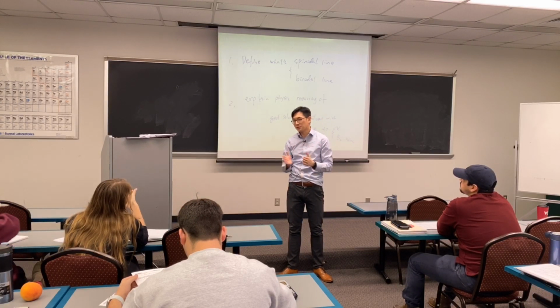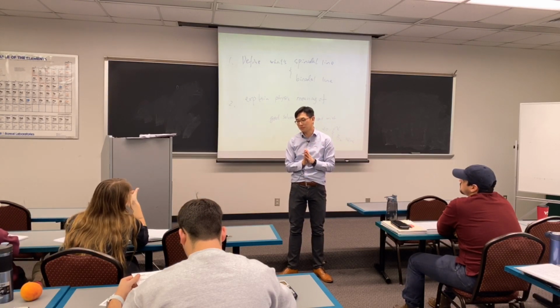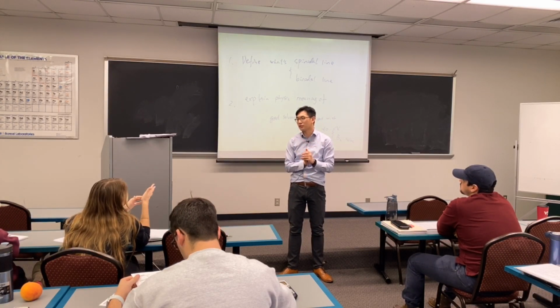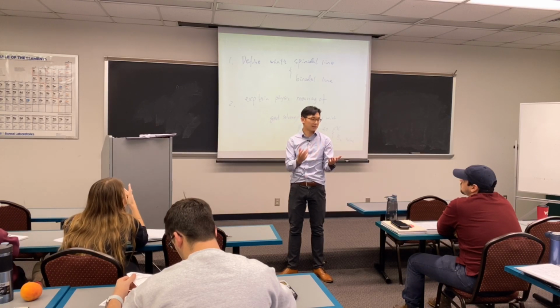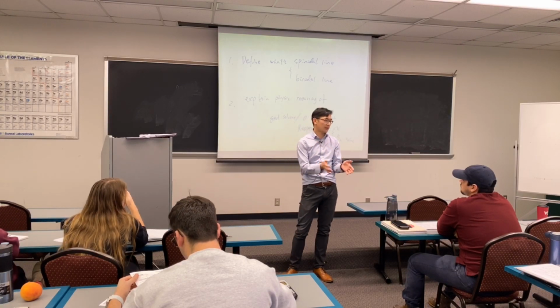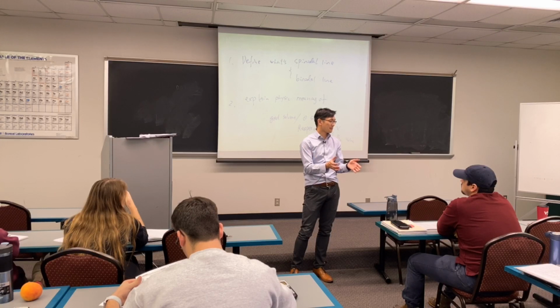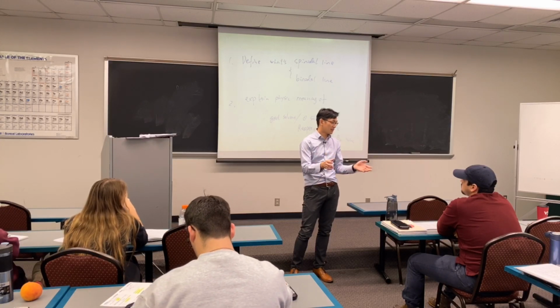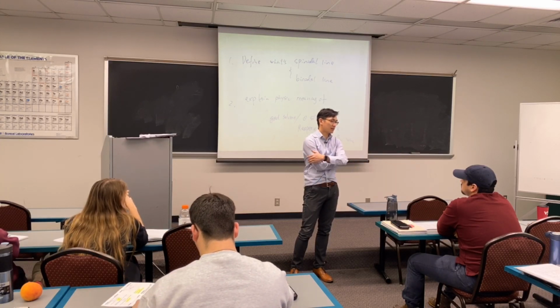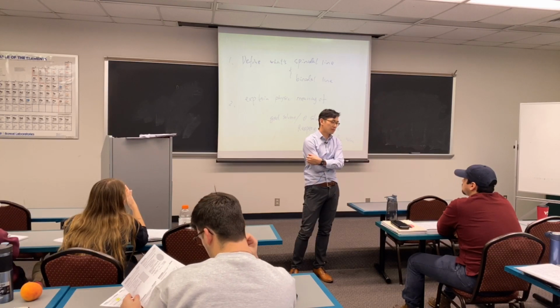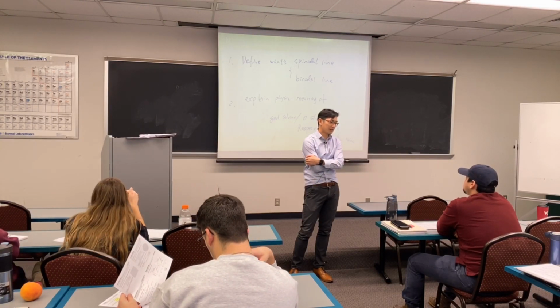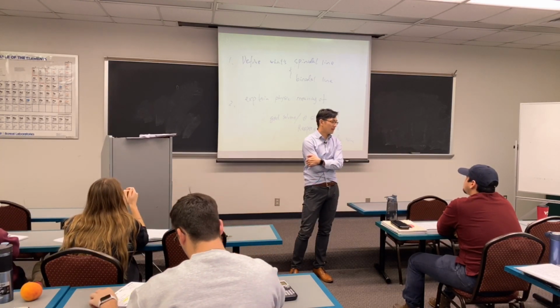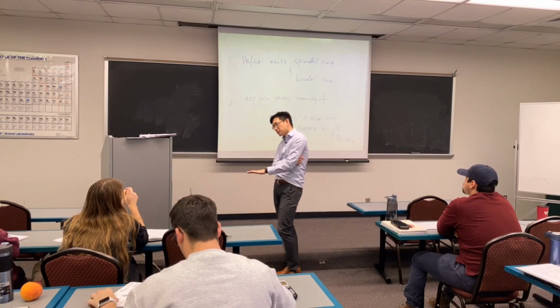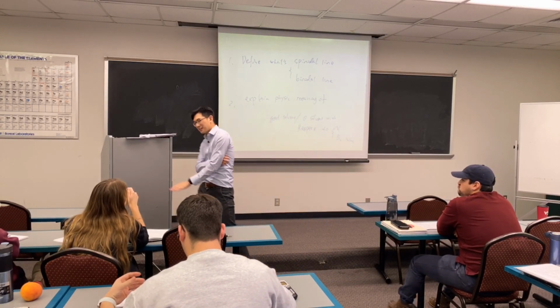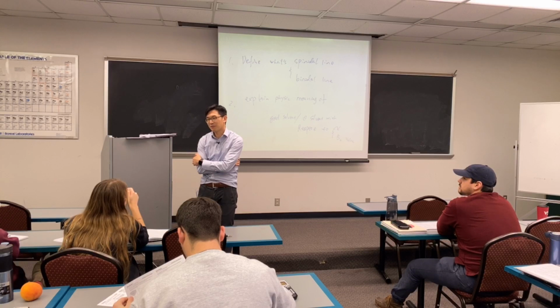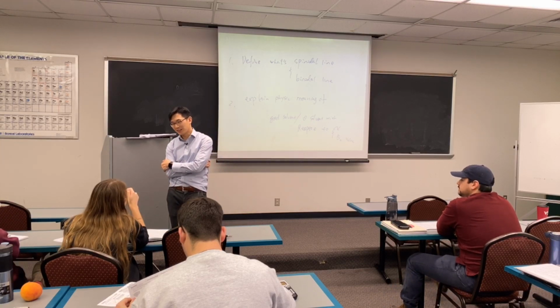What we use to create those intermixed states is basically dissolving in a solvent. So both A and B are dissolved in a common solvent at low concentration. Then we spin-coat them, and the solvent evaporates very fast. So this quenches your two polymers into intermixed states. It creates a beautiful device. It has record high performance. Nowadays, it's even competing with inorganic silicon.